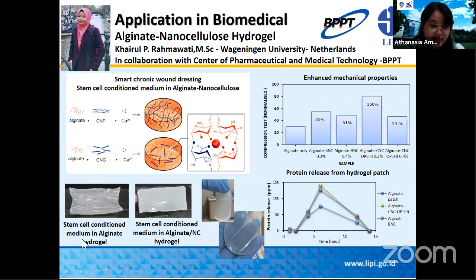As you can see here, when we incorporate nanocellulose into the hydrogel system, it helps to maintain the structural integrity of the hydrogels. Without the nanocellulose, the hydrogel may shrink and a collapsed structure can be obtained. And you can see a significant enhancement of the mechanical properties of up to 166%, which is quite impressive. That's why it can help to give optimum protein release.